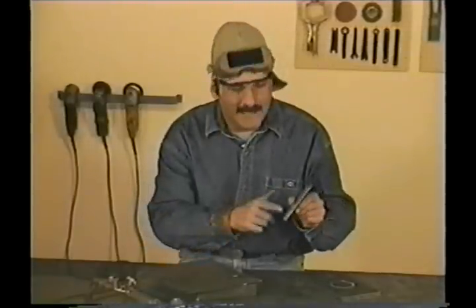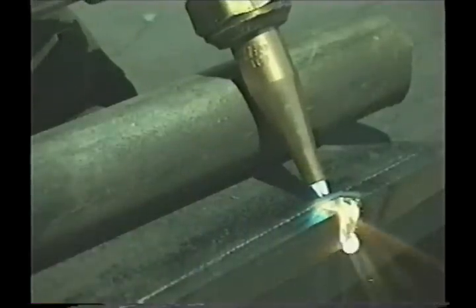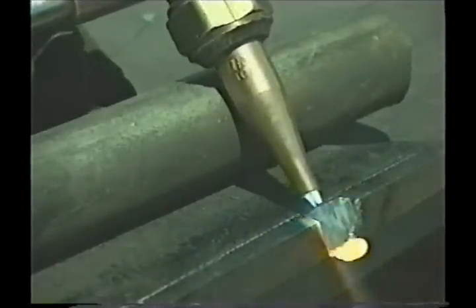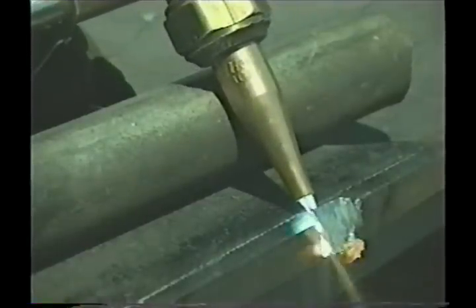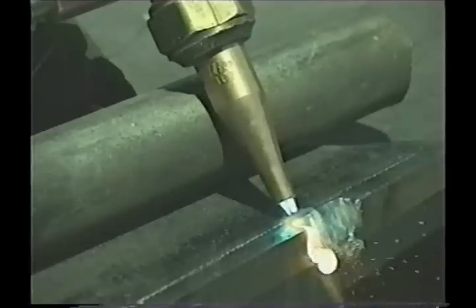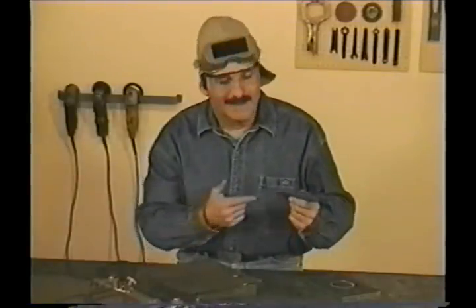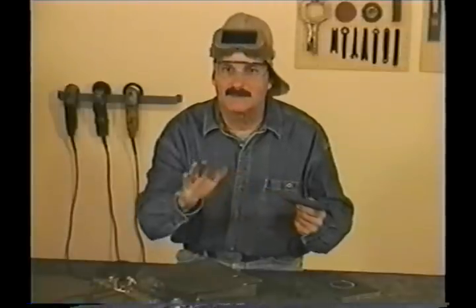Before you start, you can draw a line as a guide. Angle the torch so you're not cutting through the bottom corner. Because a lot of the heat is just blowing off the edge, the cut speed will be slower. If the cut stops, let off the cutting jet lever, jump out to the edge, preheat, cut back to the line, and keep on going. Using a straight edge to bevel helps keep the torch steady. On long bevels, cut out to the edge, reposition yourself, cut back into the line, and go again. You'll probably get slag sticking to the bottom edge because of the slower travel speed, but it comes off easily.